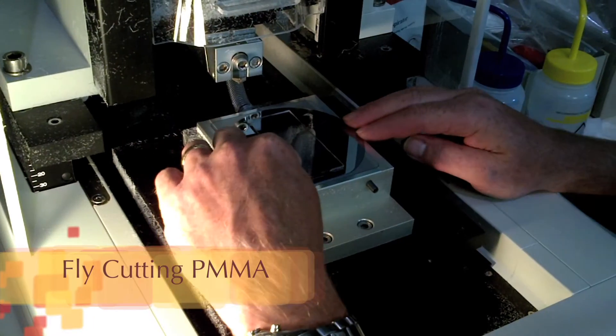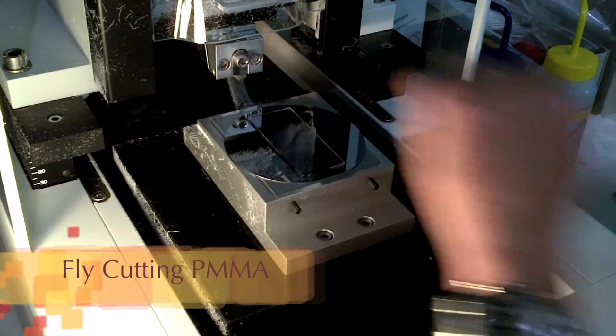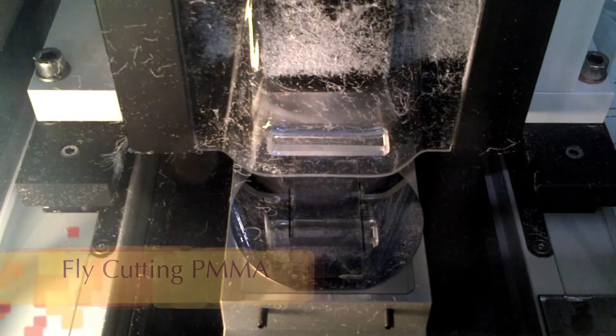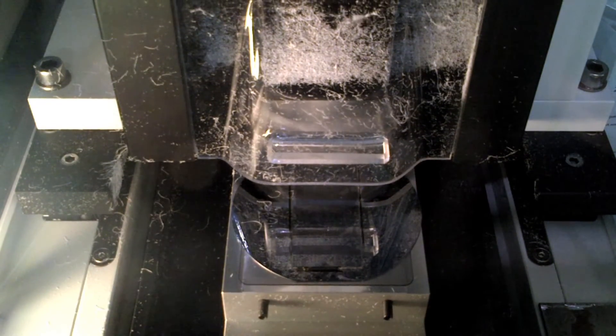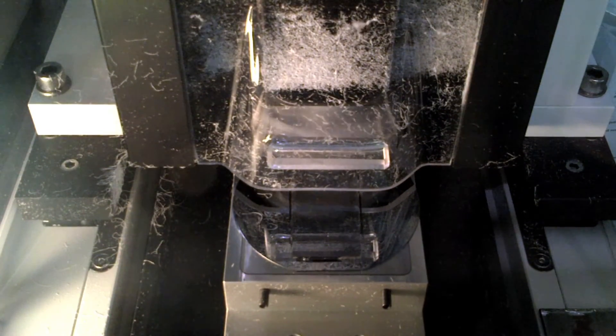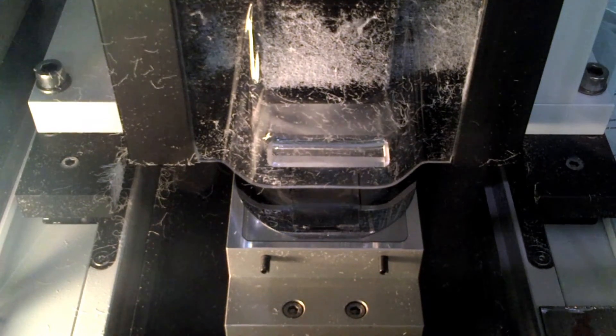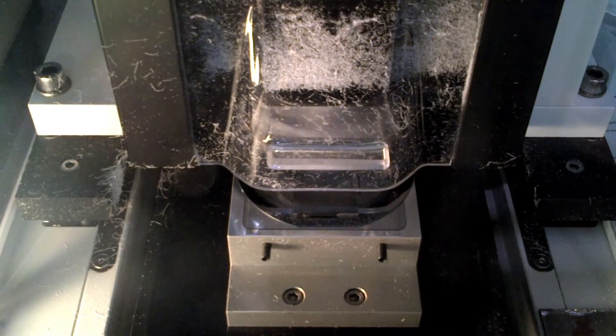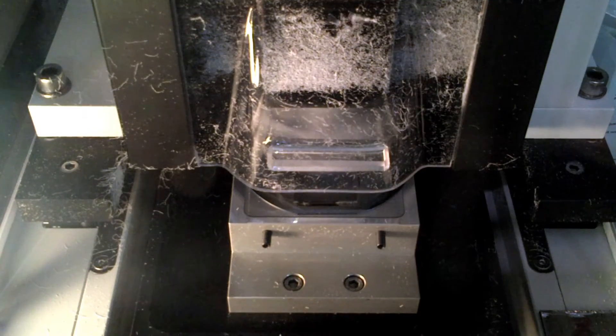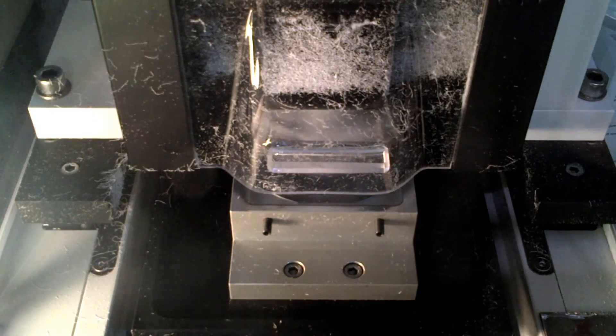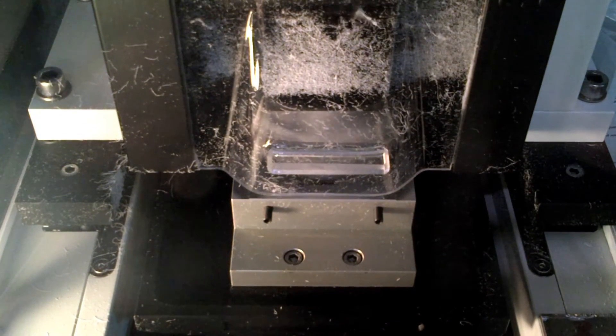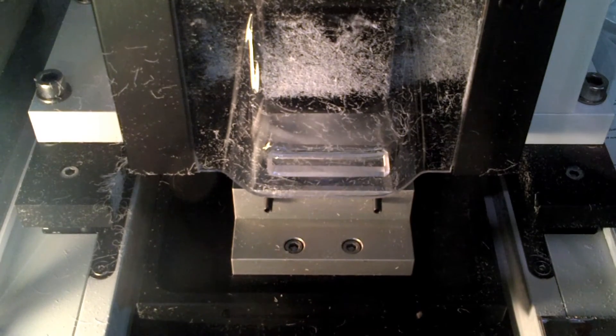The glued PMMA is then thinned down to a custom thickness requirement with a fly cutting process that uses a diamond tip. A coarse cycle removes 100 micrometers PMMA from the top surface to bring it closer to the required thickness. A finishing cycle then buffs it up to bring the PMMA to the required thickness and to have a clear optical finish.